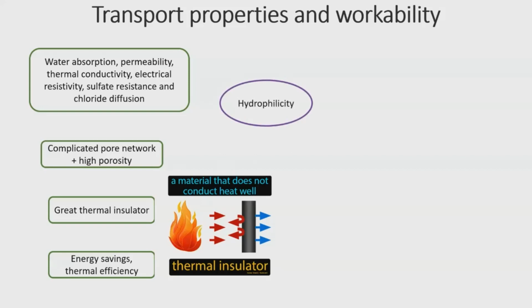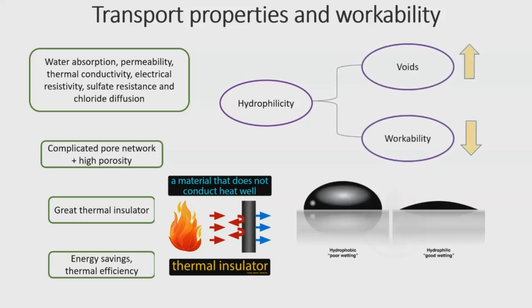Another important transport property which affects workability is hydrophilicity, or water uptake, water absorption. It tends to absorb water and then eventually release it, increasing the ratio of voids and thus decreasing workability because of this water absorption.